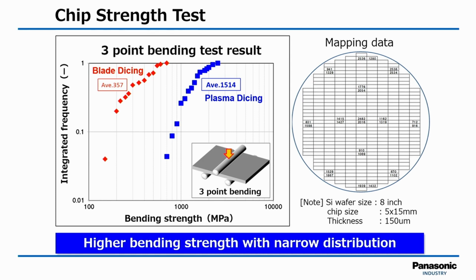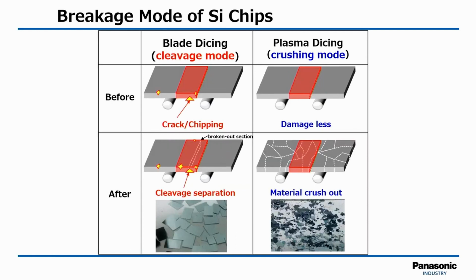Because of the damage-free result, this leads to much stronger chip strength. If we subject these chips to a 3-point bending test, as you can see here, with blade dicing on the left and plasma dicing on the right, you can see that the plasma diced chips are much stronger. Why is that? Well, in the 3-point bending test, the cracks propagate through the damage that's caused on the edge of the chip. Whereas with plasma dicing, it's actually approaching the strength of natural silicon, so it tends to crush.